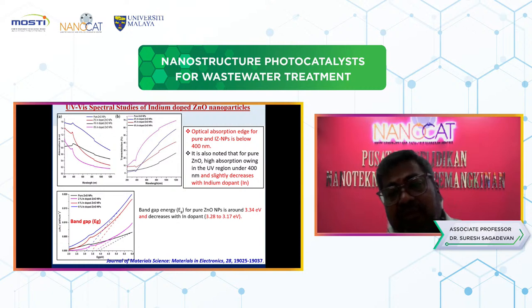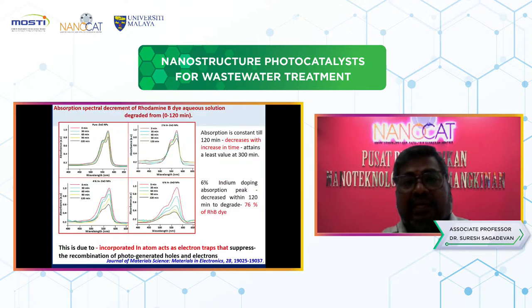The band gap energy for pure zinc oxide nanoparticles is around 3.34 electron volt, and it decreases with the indium dopant concentrations, ranging from 3.28 electron volt to 3.17 electron volt. We then studied the photocatalytic activity using the rhodamine dye in aqueous solution for a time period of 0 to 120 minutes, using UV light radiation from a mercury lamp.